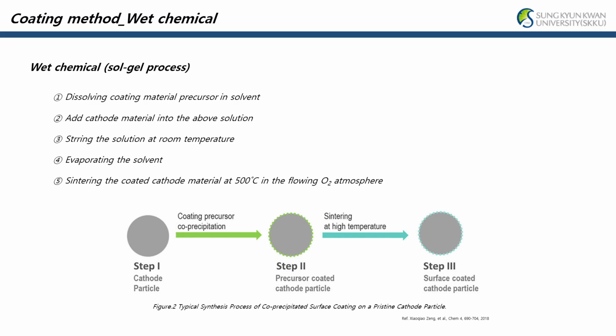First, dissolve the precursor of the coating material in the solvent, and then add a cathode active material to the solution and stir it at room temperature. Then blow away the solvent and sinter at 500 degrees under the flow of oxygen to create a coated cathode active material. This process is to coat the cathode material with a coating precursor first, and then synthesize it during the sintering process so that the desired coating material is finally coated on the cathode material.